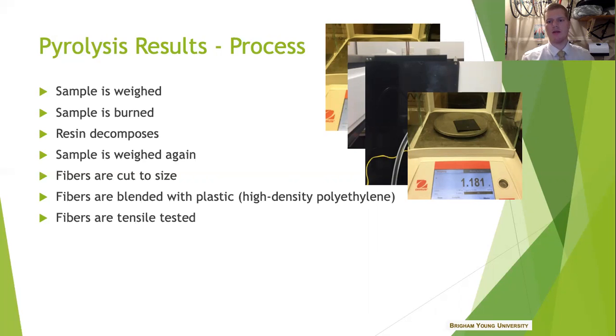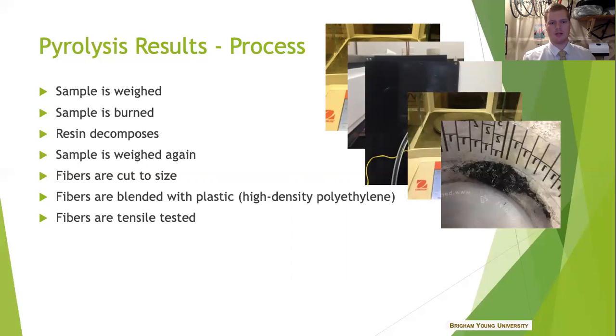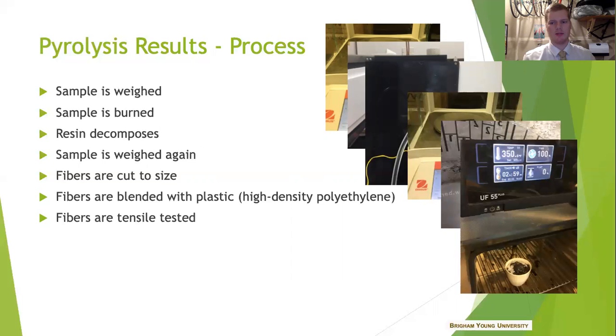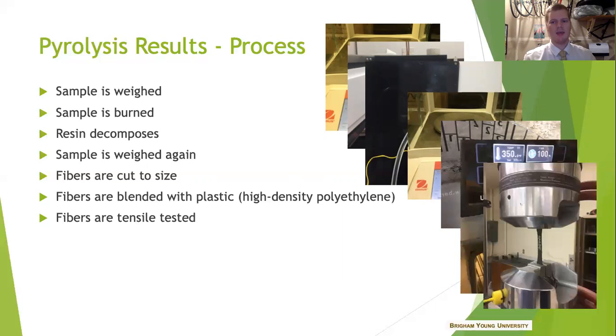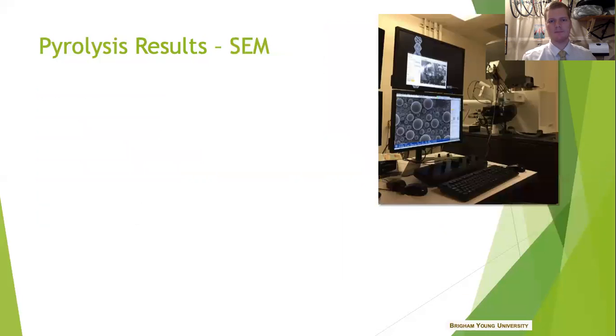And then I was able to compare that to the known resin content to determine what percentage of the resin I was burning. And I was really happy to see that for both processes, most of this resin was going away. So then in turn, the fibers were cut to size, about 3 millimeters in length, and then blended with high density polyethylene in an oven at 350 for about 3 hours, and I would mix them. And then the fun part, go ahead and loading them up on our tensile testing machine and getting some data from it to see, okay, which of the recycled carbon fibers blended with that HDPE was the best.